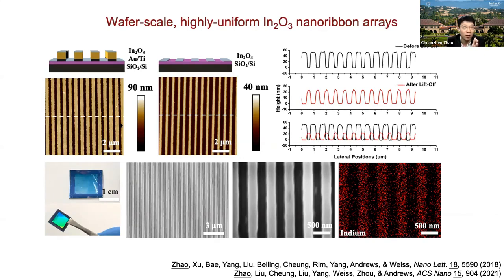Actually, this dark one is a little bit narrow, and this yellow one is a little bit wide, and this becomes more apparent when I flip over the size. But that was not from the patterning, but more like a remolding process, when we remove the PDMS from the CDs.